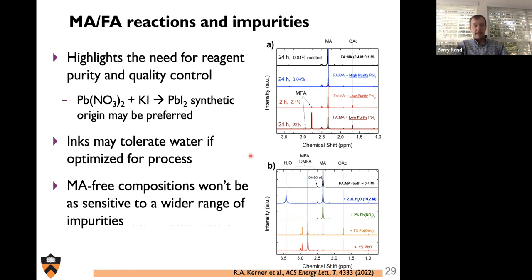So what this work does, again, just published a few days ago, is it really highlights the need for proper reagent control, and that purity does indeed matter for getting results that will be generally reproducible. It also tells us that inks may tolerate water if we can properly design the ink, which is important for commercialization purposes, because often doing things completely water-free is not particularly realistic. Also, but we don't necessarily have a perfect solution to this, is that methylammonium-free compositions will not be as sensitive to these deprotonation impurities as methylammonium-containing systems will be.